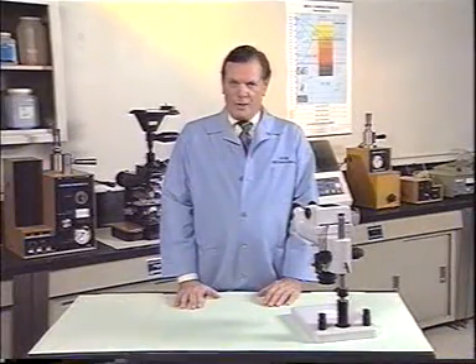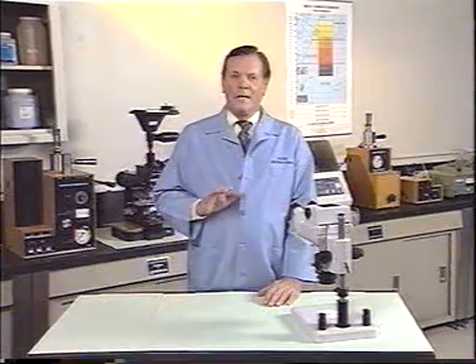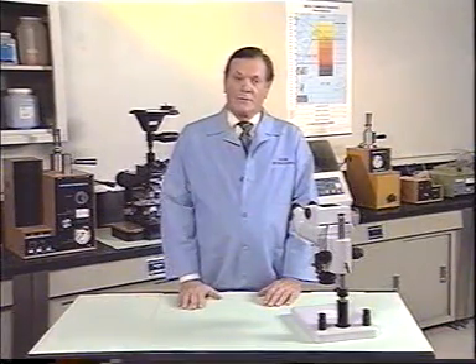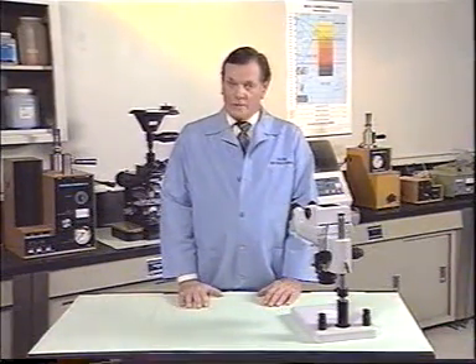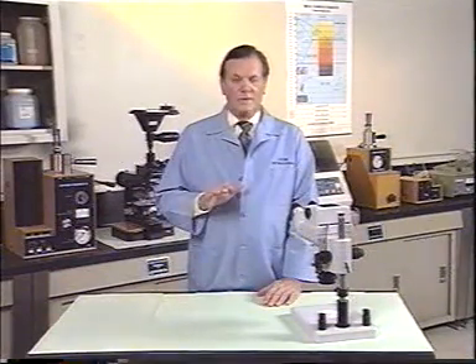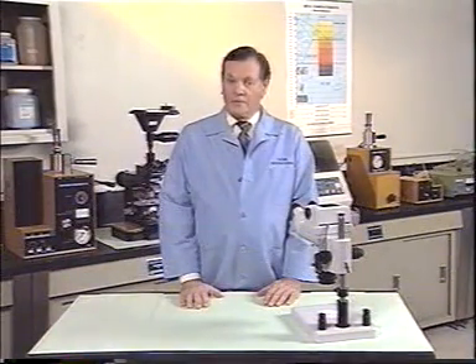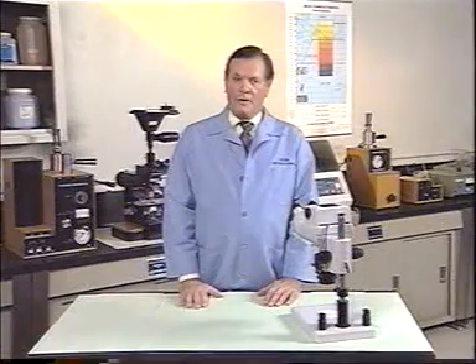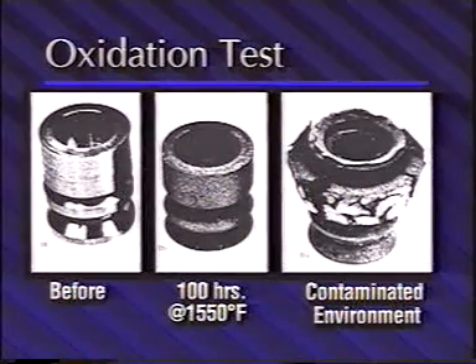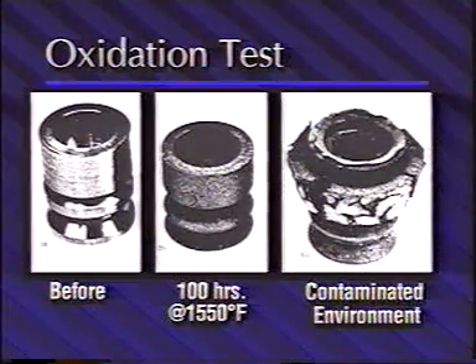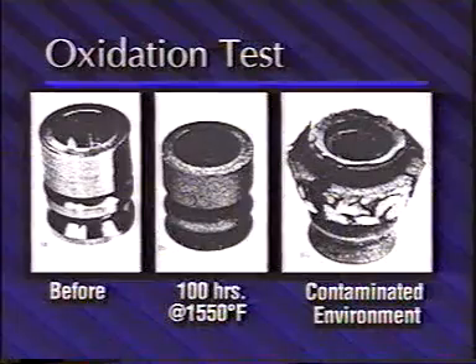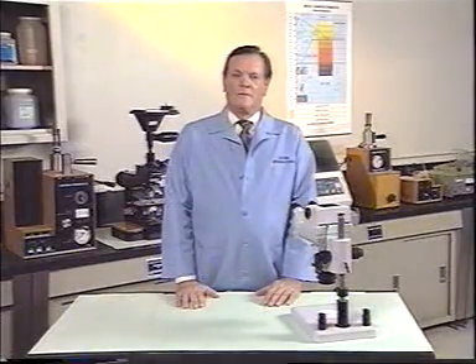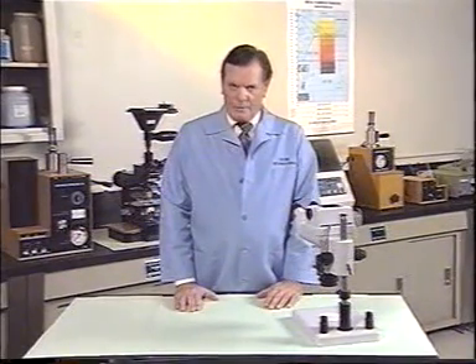Oxidation corrosion burner rigs have been developed to test turbine blade alloys and coatings. These test rigs are capable of testing 8 to 12 specimens under engine conditions at temperatures from 1450 to 2300 degrees Fahrenheit. The basic steady-state oxidation test simulates aircraft cruising conditions. Higher than cruising temperatures are obtainable to accelerate degradation. These are just a few of the tests available for detecting and simulating failures that can occur at elevated temperatures.